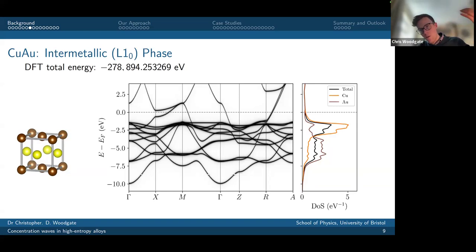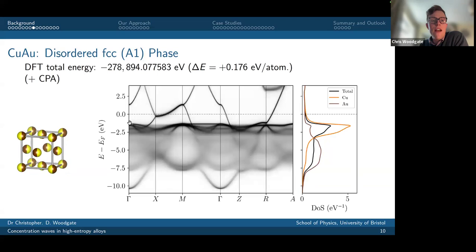Okay, but if I look at the disordered FCC phase, what's known as the A1 phase, here I've done a KKR-CPA calculation where I'm using the CPA to describe the electronic structure of the disordered alloy. What I see is that my band structure becomes really heavily smeared, because if I imagine I'm an electron propagating through the material, I'm not seeing a regular periodic arrangement of atoms. As I move through the material, I might see a gold atom, and then suddenly I encounter a copper atom. Although I have this underlying crystal lattice, the periodicity is broken because of the changed chemical identities of the different lattice sites. And what this means is that even if I cool the material down to 0 Kelvin, the Bloch states are no longer eigenstates of the system, and there is a finite electronic mean free path, and therefore a finite residual resistivity.